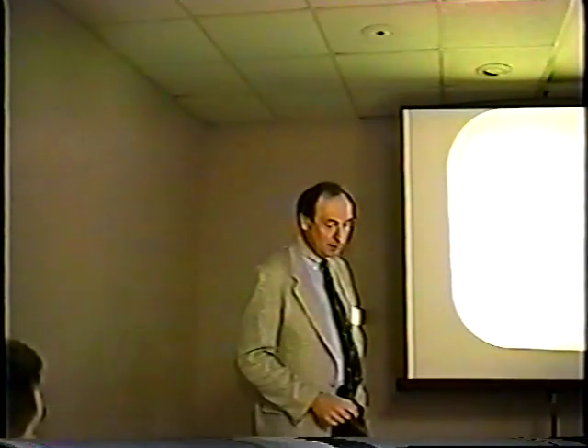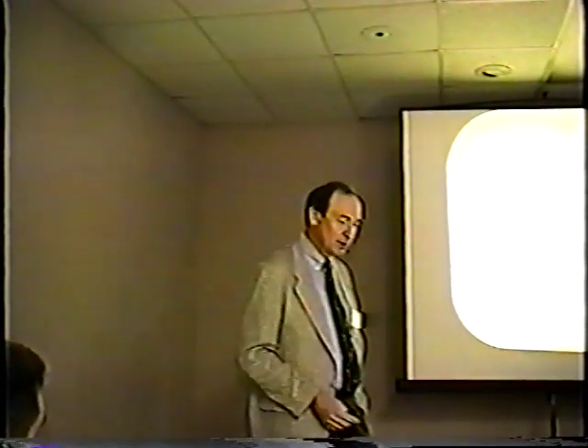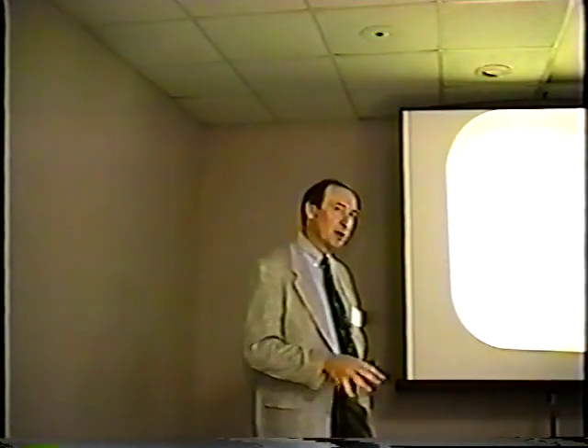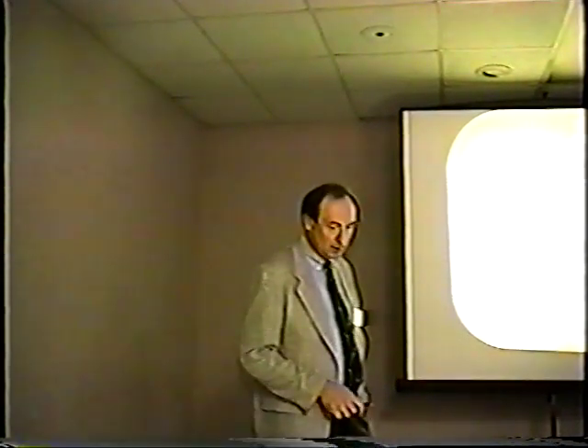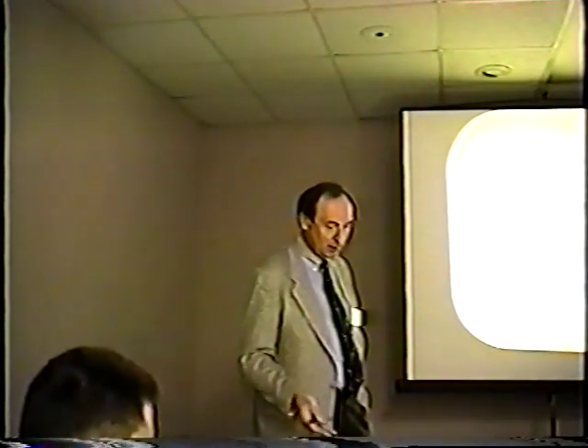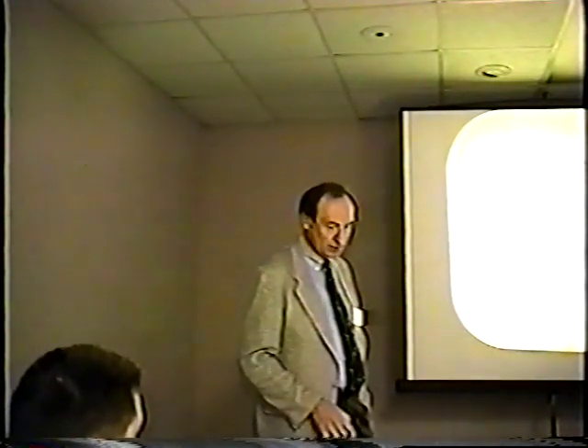The other thing that we've looked for are other elements on the electrodes by XRF. That's been a little bit spotty. We've seen some aluminum, but I don't think there's any reason to believe that that's not something that's already just in the material, or could come from the system. And we've seen antimony, and that could be from solder, which was used in some of the other ones. Right now we're spot welding everything.